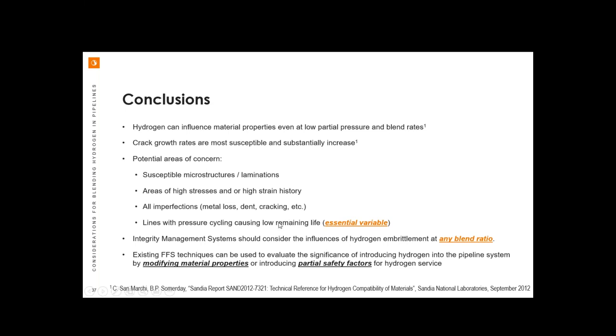We note that pressure cycling and how we operate our lines is an essential variable. We talked about how the crack growth rate is directly proportional to the amount of imposed cycles on a pipeline. So we should play with the levers that we have. We should reduce the amount of cycling as much as we can. And the data really suggests in the literature that we need to be concerned about hydrogen at any blend ratio. And of course, we've explored, at least from an introductory perspective, for a few types of imperfection types, what we may have to do to modify the fitness for service techniques, either by accounting for degradation in material properties or introducing additional partial safety factors.